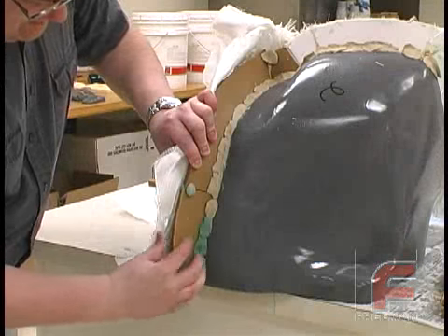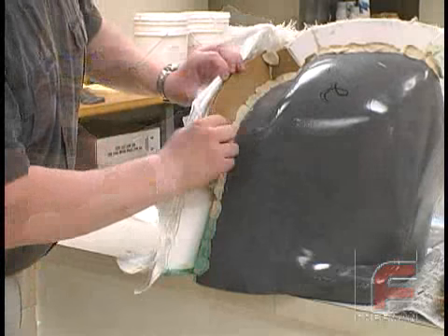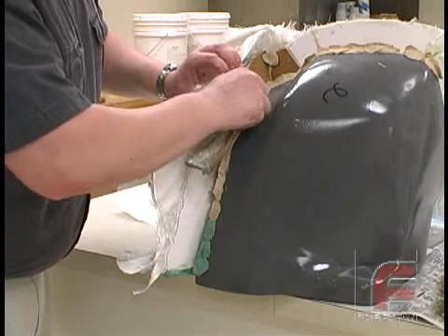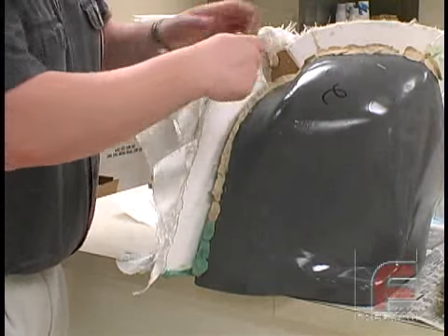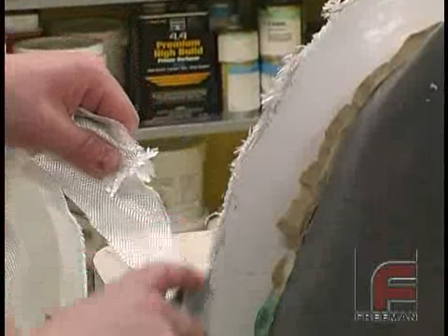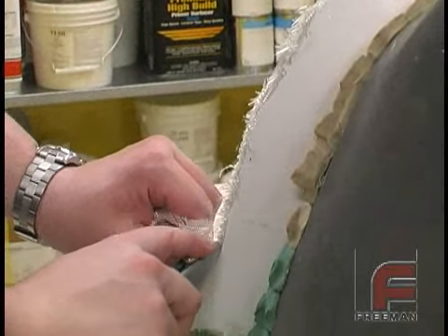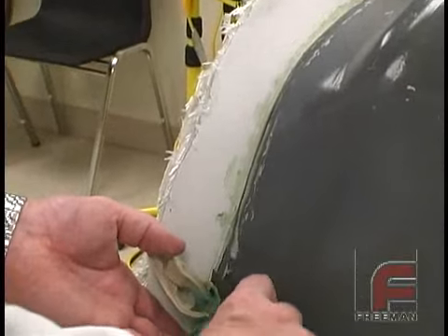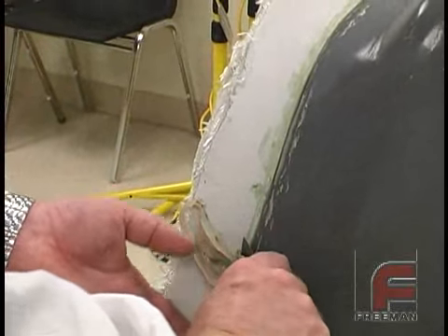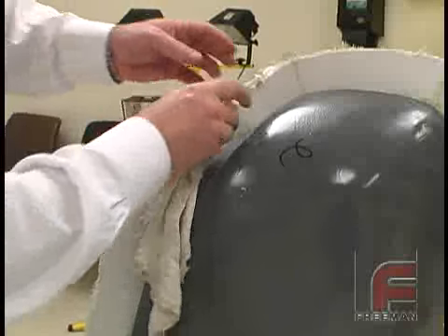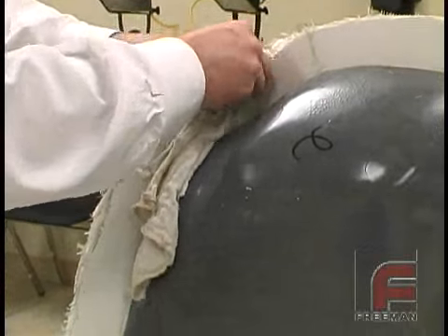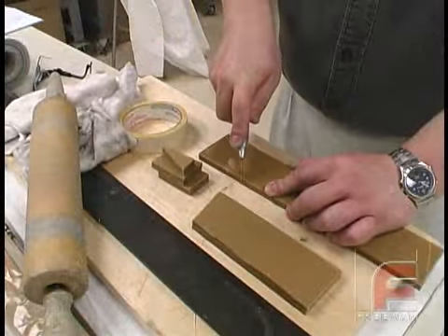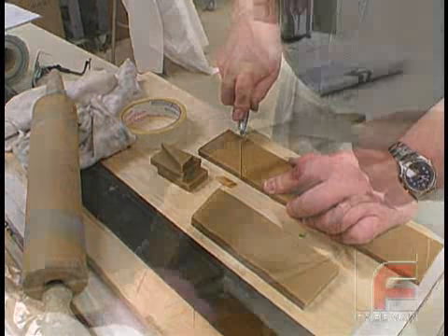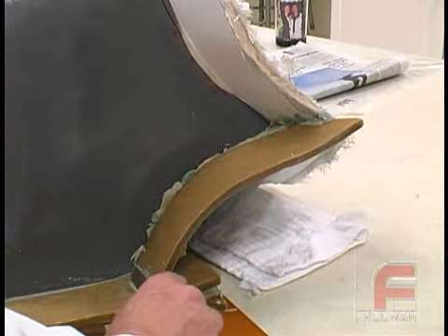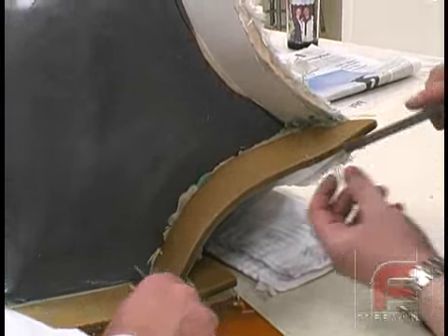After 16 to 18 hours, we are ready to create the second part of our mold. We begin by removing the sheet wax that formed our parting line. Then, using a razor knife, we clean up the edges of our fiberglass layup. To clean up the clay that was used to attach the sheet wax, we use a fillet shaper tool to scrape the clay and a rag to wipe off the remainder. Next, we attach new pieces of sheet wax to complete the second parting line. Again, we're using Plasticon modeling clay to adhere the wax and our fillet shaper tool to clean off the excess.